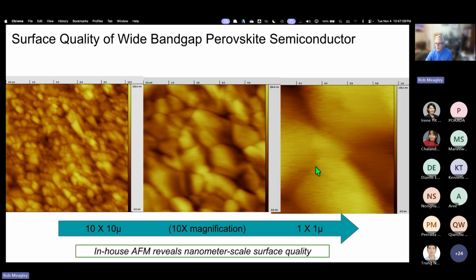But then when we go down to a 1 micron by 1 micron field at the junction between 3 crystals, you can see very clearly the nature of the junction, the fact that we've got definitely twinning happening there, and a good image of what the pit actually looks like, and that it is a fully contiguous coating, that the dark regions are just quite deep, but there are no pinholes, and it's a truly beautiful, well crystallized surface. And I suppose the moral at the bottom of this slide has been repeated, but it stands repetition. There's just no substitute for resolution.